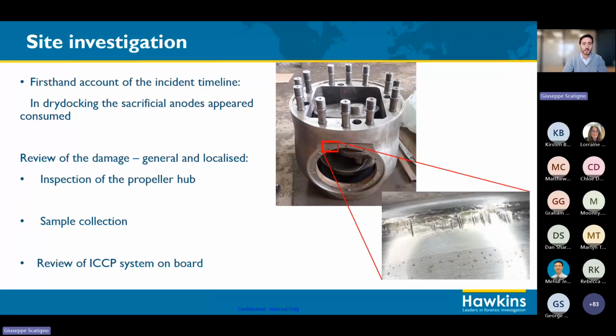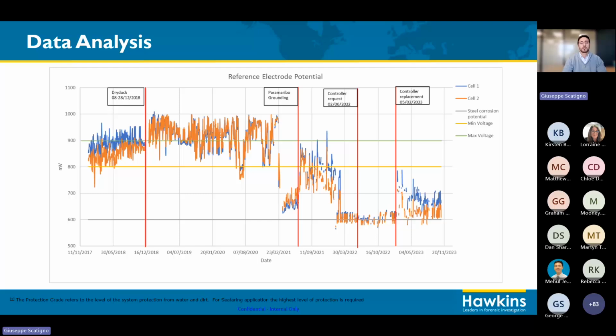I also saw firsthand the ICCP system on board, in order to try and understand if it had been wired correctly, if everything was as expected, and then compare that with the information that I received from the owners of the vessel. Now, all you need to know about this graph is that if you are in between the yellow and the green line, your hull is happy. Your hull is adequately protected, it's not corroding. If we are below this lower threshold, the metal is effectively exposed to the seawater as if it was bare metal, as if we were not protected.